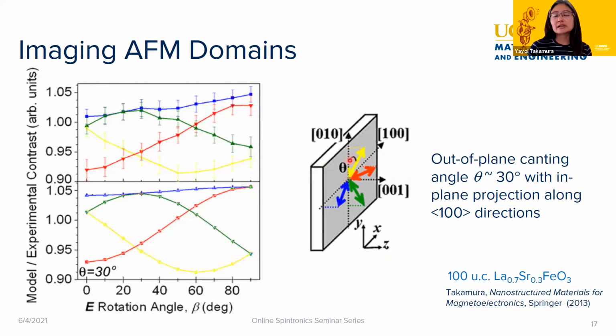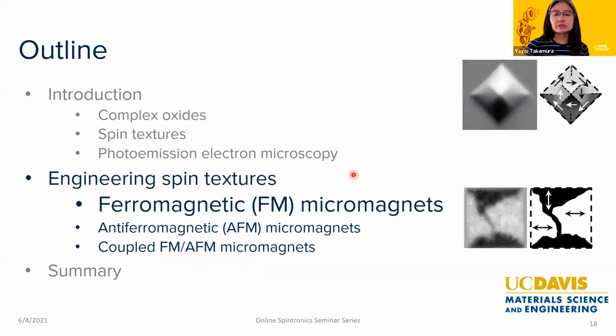And what we can determine is that the canting angle out of plane is 30 degrees. And then their in-plane projection is along the 100 family of directions in the material, right? So it's a way to really be very particular in terms of mapping out your antiferromagnetic domain. So it's a much more laborious process to map out antiferromagnetic domains than ferromagnetic domains. Okay, so hopefully then you have an idea of how we do these measurements, and how we interpret what the antiferromagnetic spin axis is doing.